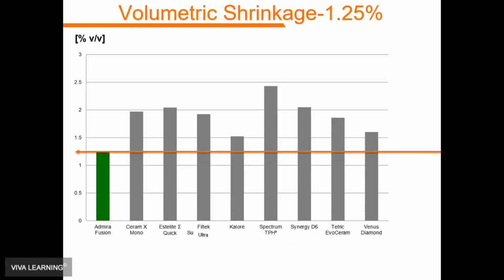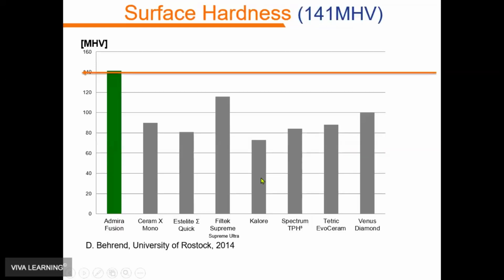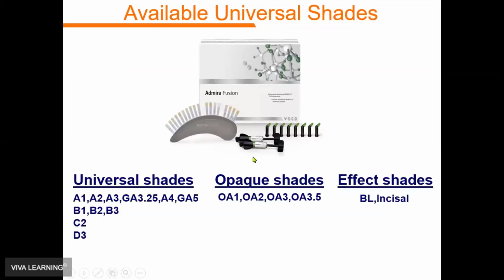Volumetric shrinkage today should be anywhere from 1%, maybe up to 1.5%. With Admira Fusion and Admira Fusion Extra, we're about 1.25%, which is certainly a good number today, what you want to shoot for. The surface hardness is due to a lot of different things. It's very high because the glass fillers are highly filled at 84%. And with the resin content, not with free radical monomers, there's less resin in there. That means there's going to be more filler and it creates a harder surface and edge strength as well.